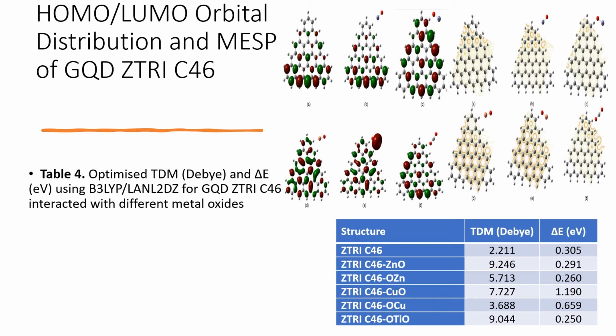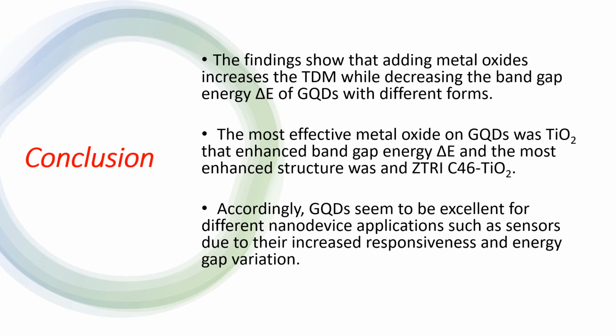Finally, in the case of graphene quantum dot zigzag triangle form, metal oxide changed the orbital distribution and the color map of molecular electrostatic potential, which increased the reactivity of the graphene quantum dot surface. Also, total dipole moment increased and band gap energy decreased with metal oxides, and the most enhanced metal oxide was titanium dioxide with band gap equal to 0.25.